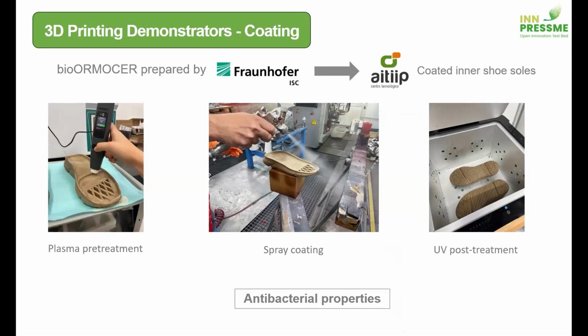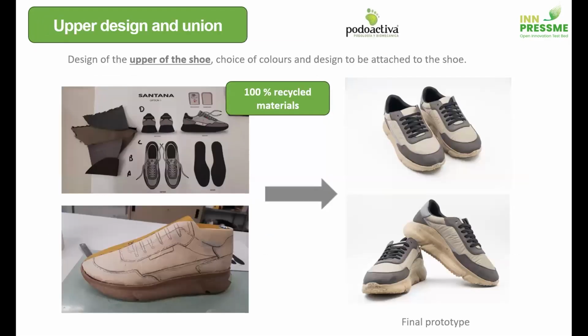And again, with the coating from Fraunhofer, we coated one of the pairs, not to try the antibacterial properties, which were already tested at lab scale with really good results, but to see if the coating would have any effect on the material when submitted to the validation tests. Once we at IT printed the soles, they were passed to Podoactiva, because of course you need the upper part to be able to validate the shoes. They decided to use 100% recycled materials to give the whole design a complete eco-friendly demonstrator.